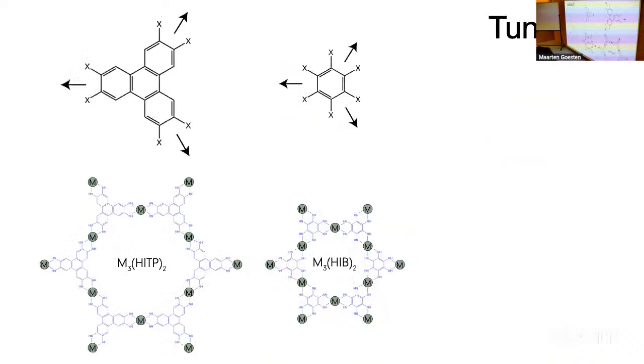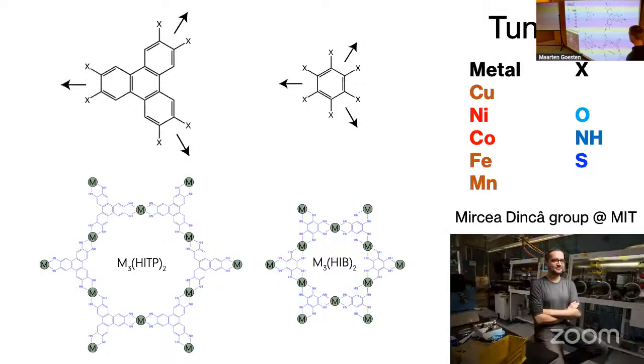These systems are great. What we can already do is tune the pore size using ligands that will symmetrically give you the same geometry. So this is a four-ring triphenylene, they call this. And this is just hexaminobenzene. They have the same geometric properties, but you get a different pore size, and we can play around with that. So this is important.